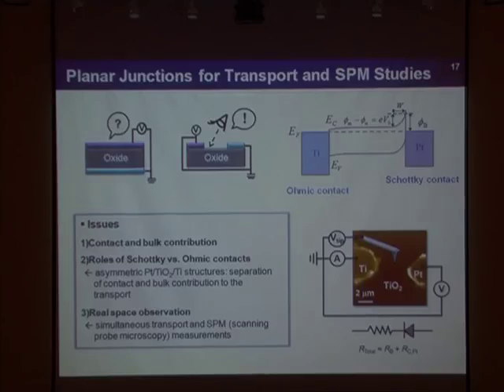Up to now I've talked about macroscopic characterizations, but we still want to see the actual interface. So we prepared planar junctions instead of conventional vertical junctions. Here we can see directly the bulk region and the contact regions, and here are example images. We deposit titanium electrodes to form ohmic contacts, and the other side of the platinum forms the Schottky contacts.